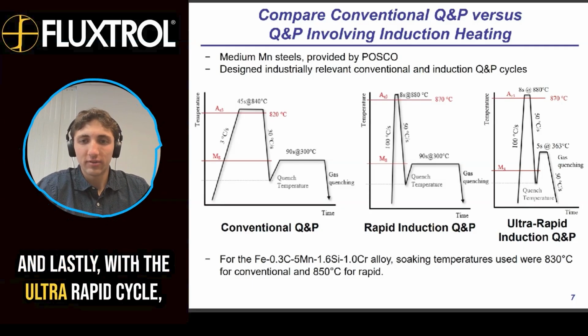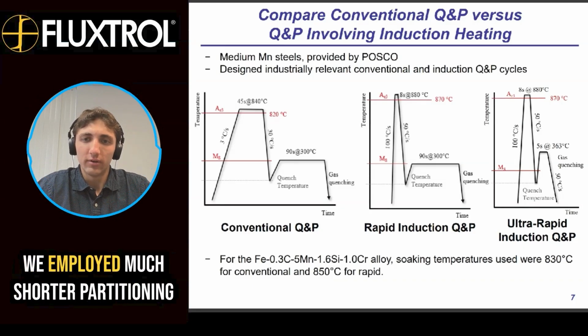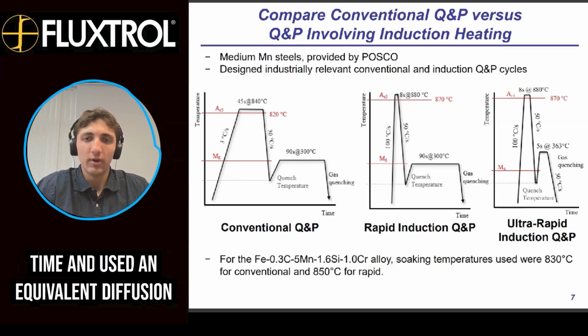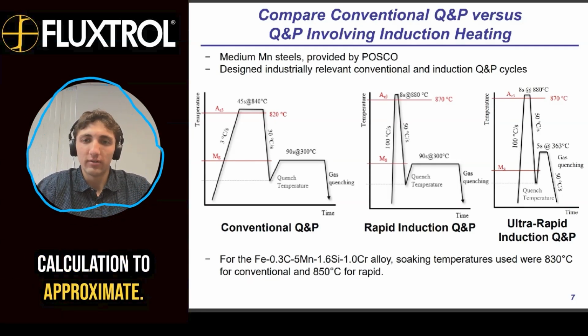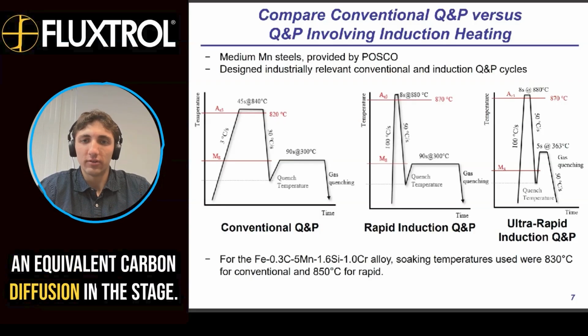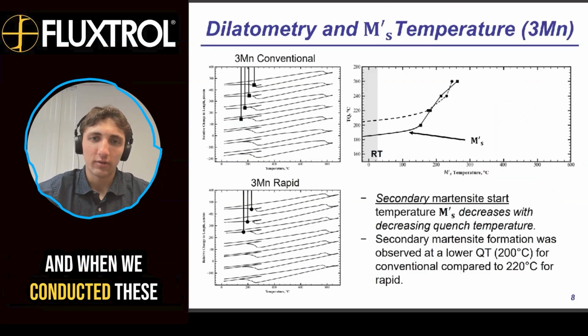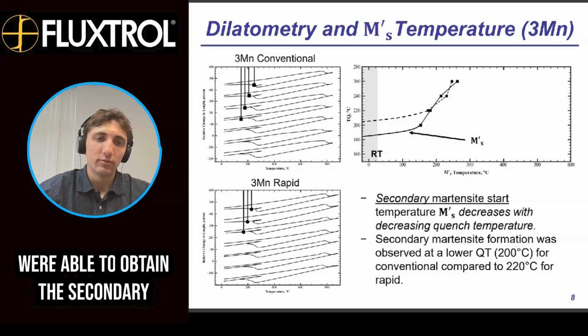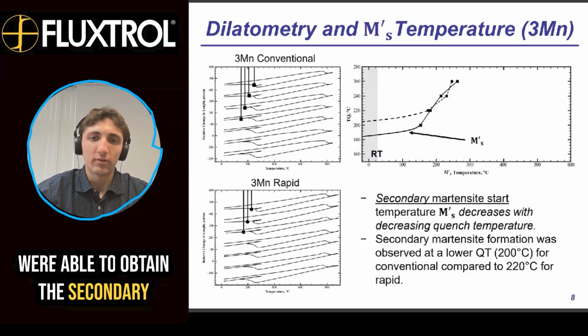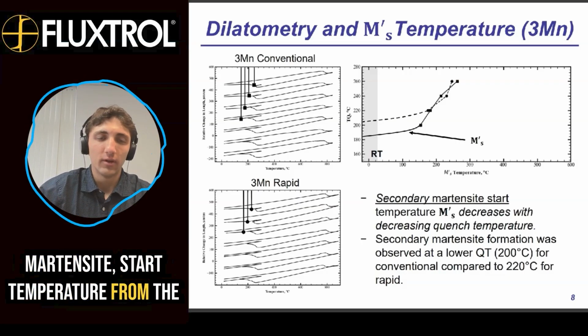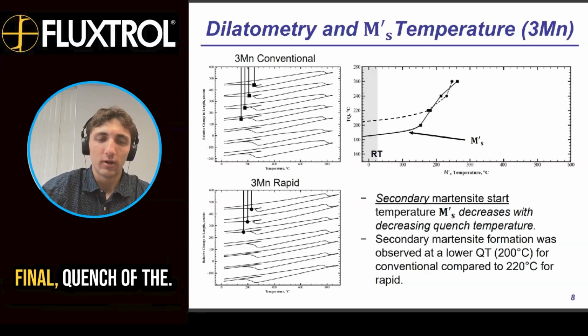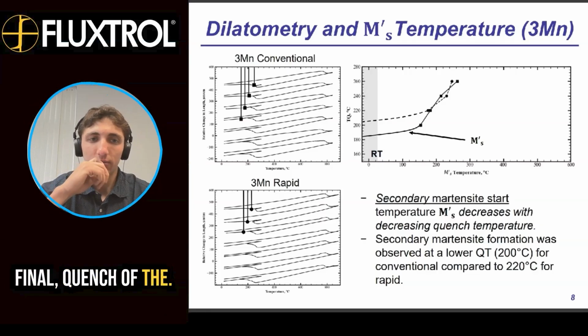And lastly, with the ultra rapid cycle, we employed a much shorter partitioning time and used an equivalent diffusion calculation to approximate an equivalent carbon diffusion in the stage. And when we conducted these cycles using dilatometry, we were able to obtain the secondary martensite start temperature from the final quench of the curve.